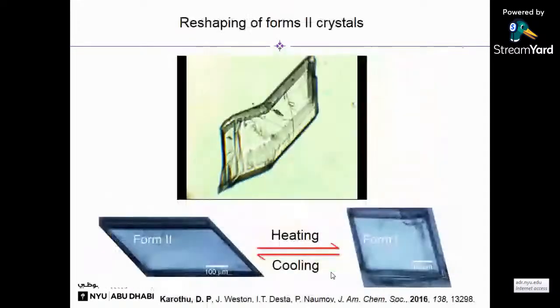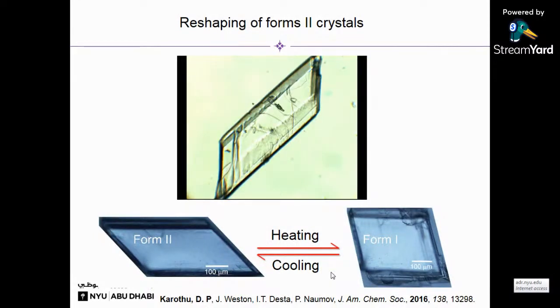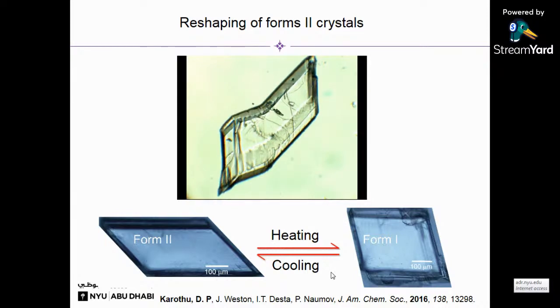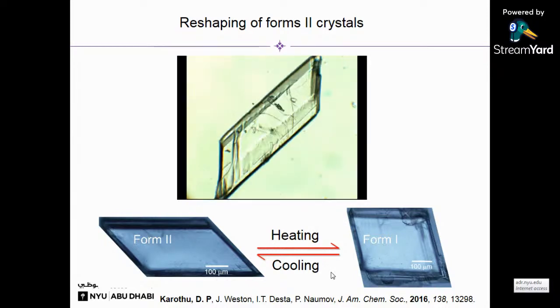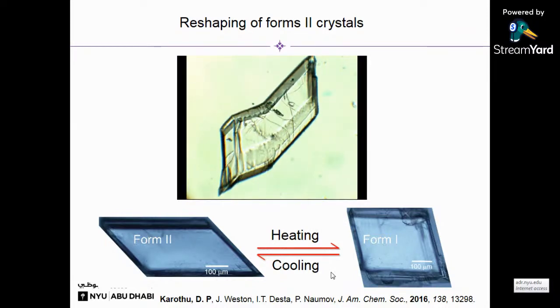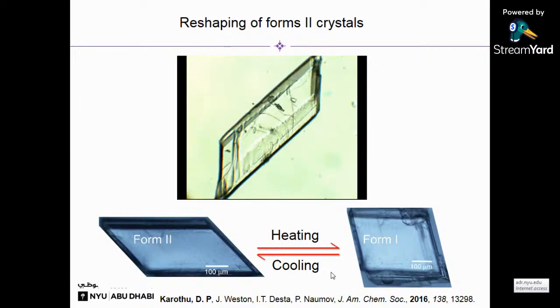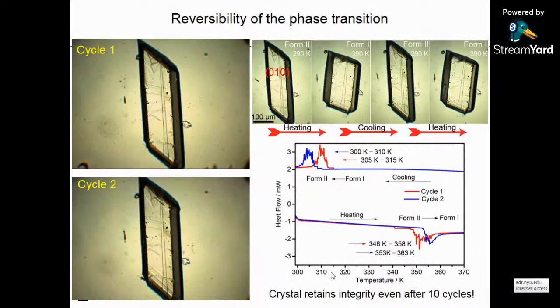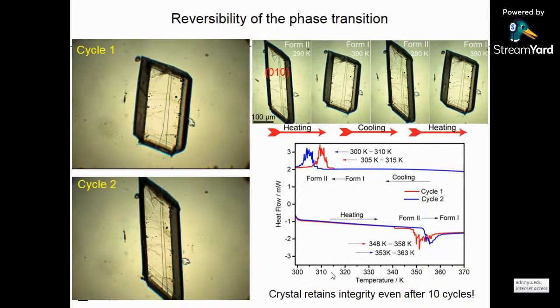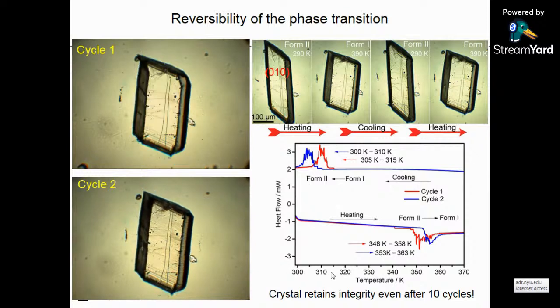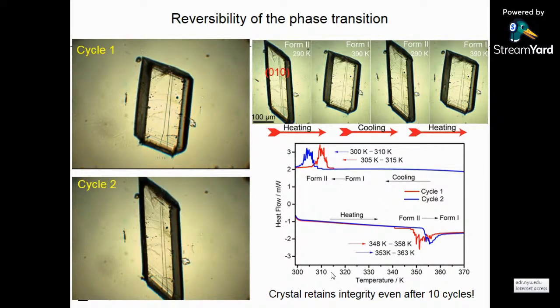But what happens when you restrain this jumping? You place a thin layer of oil, and on top of that you place the crystal. The crystals actually show a remarkable transformation from one form to another. As you can see here on the left side, this is a parallelepiped shape, and it comes to a near square-shaped structure, and this is reversible. You can do a number of cycles. At least I did 10 cycles. I did not see any kind of deterioration. You can also see here, this is the first cycle and this is the second cycle. You don't see any change between these two cycles.